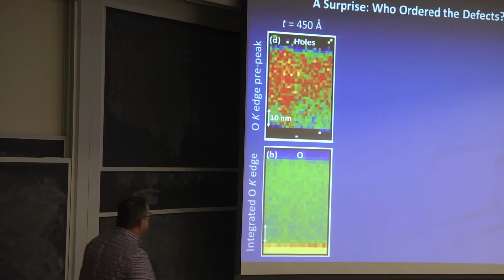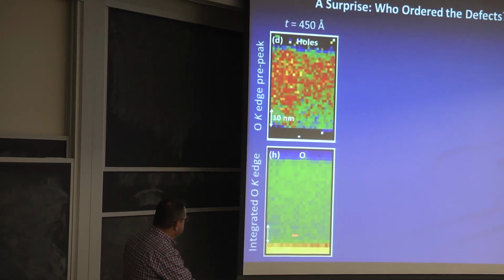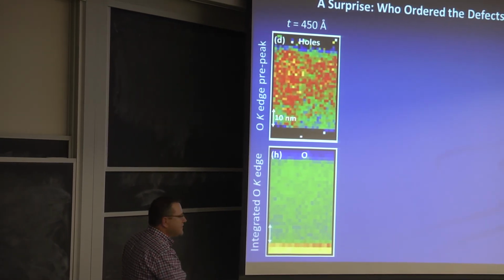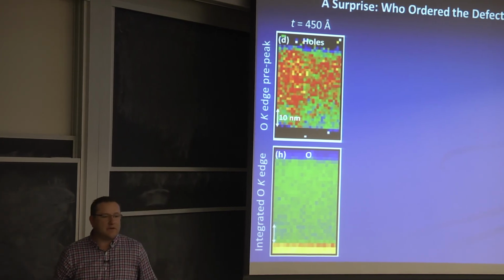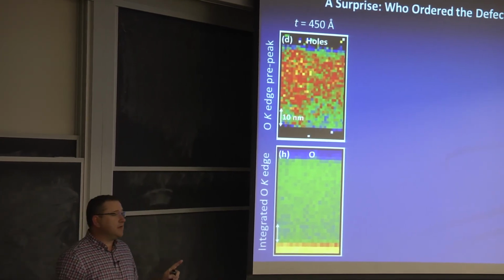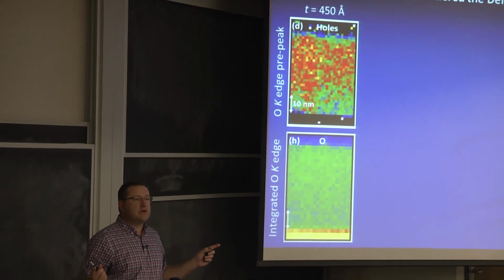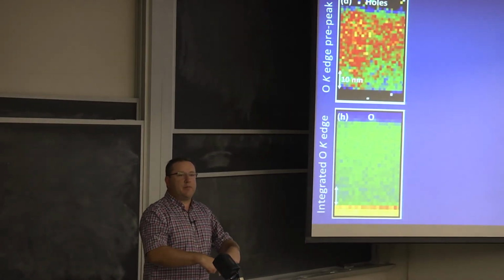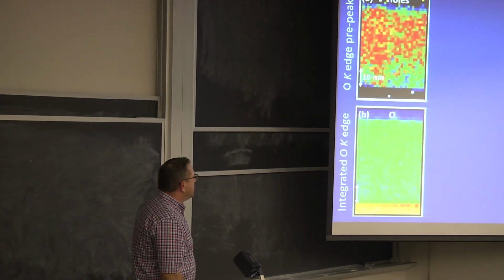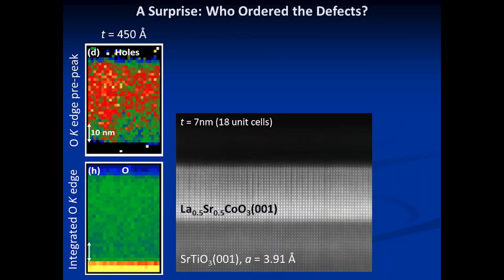Why doesn't it have any holes left? Well, we also mapped the oxygen, and it turns out there's about 2% less oxygen on the bottom. So somehow we like to make oxygen defects called vacancies, literally missing oxygens, and those oxygens like to pile up on the bottom, okay? Why does that happen? Well, this was the key image in this piece of work that we did.